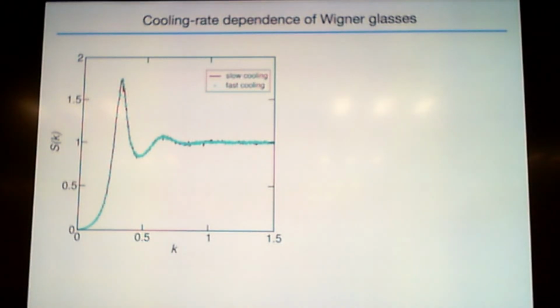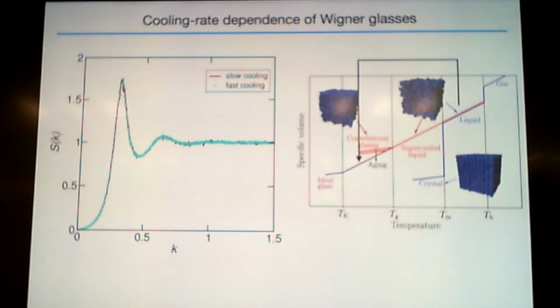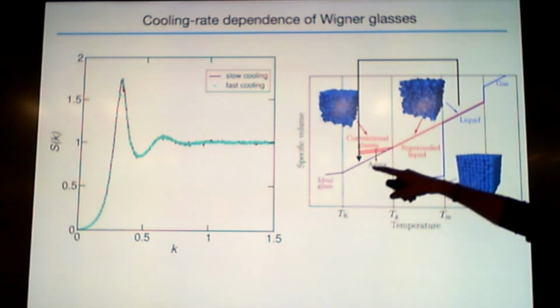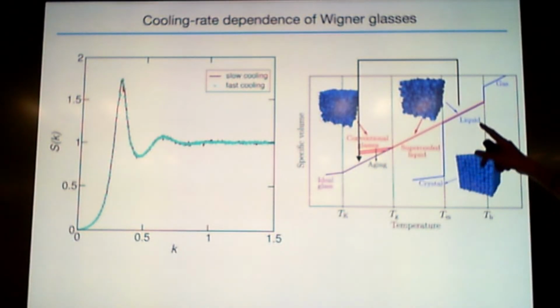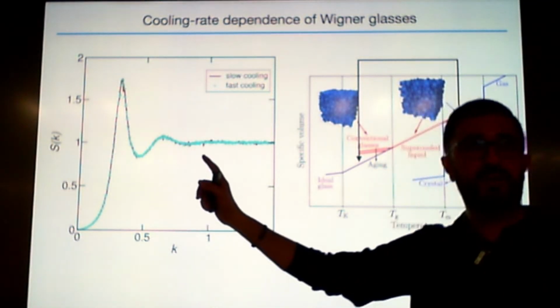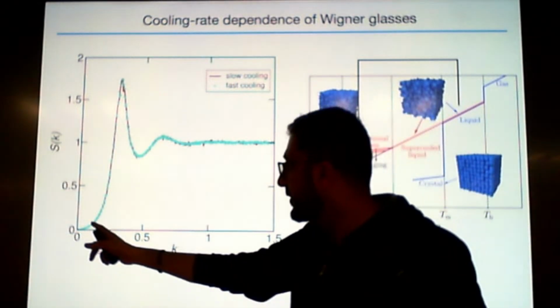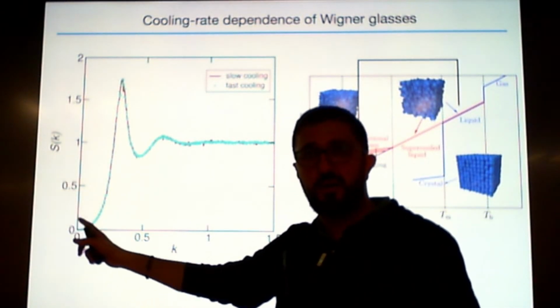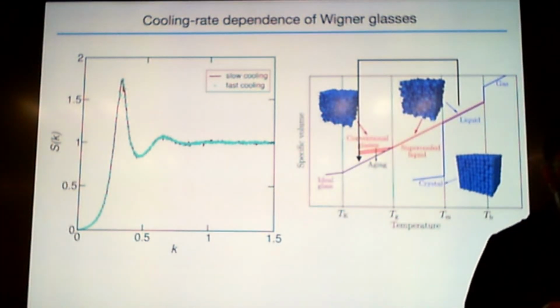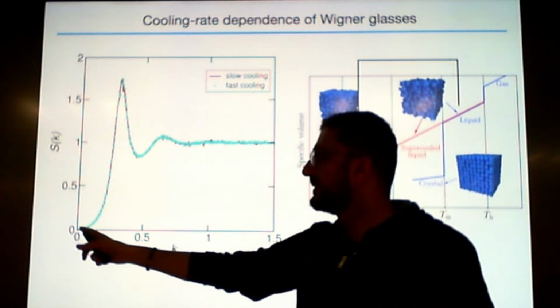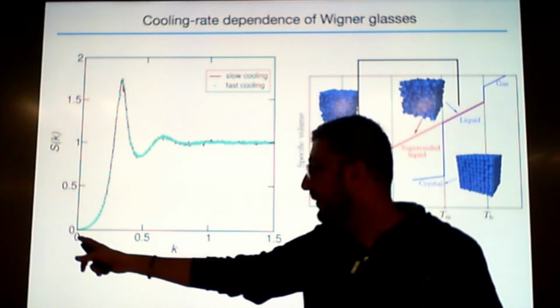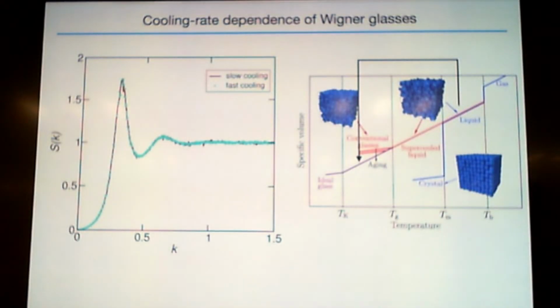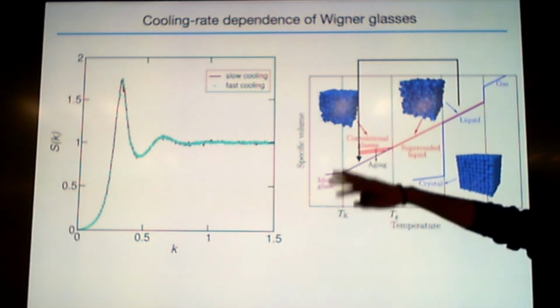So here's also a very interesting phenomenon, and then I will stop. We use different cooling rates. We cool very abruptly, we cool slowly, we cool more slowly. The structure factor doesn't change at all, except at one point, which I'm not showing you, at very small k. The large scale correlations, the structure factor, change only there, for very small k, for very long length scales. Everything else stays the same.